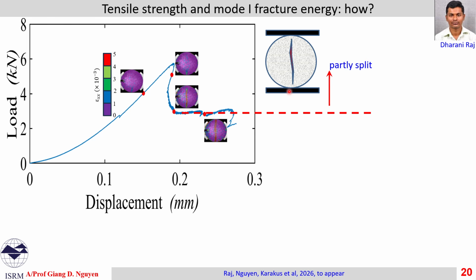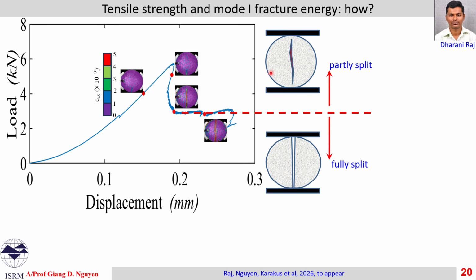This is different from the standard test using a 3-point bending configuration. The load in a 3-point bending test drops to 0 at the end of the fracture process. For the Brazilian disc test, if the specimen is fully split, the two halves can still hold a significant amount of load. And the point here is to identify the moment of full fracture.